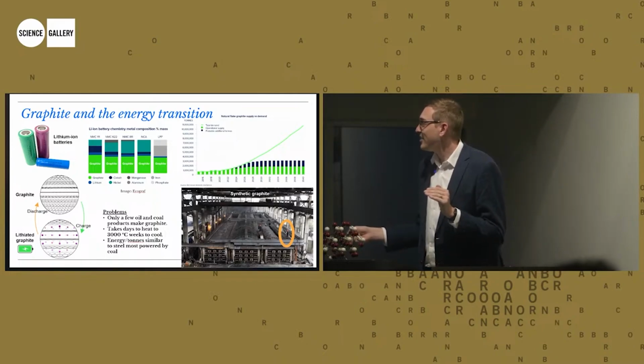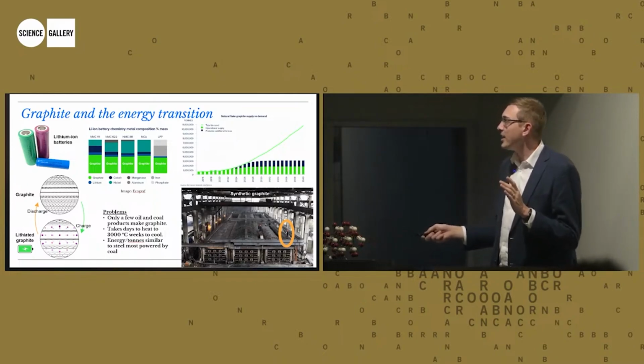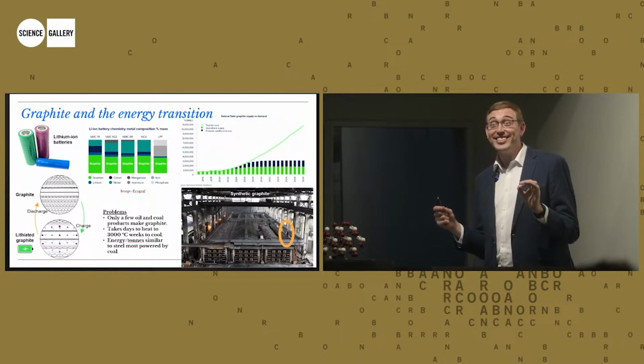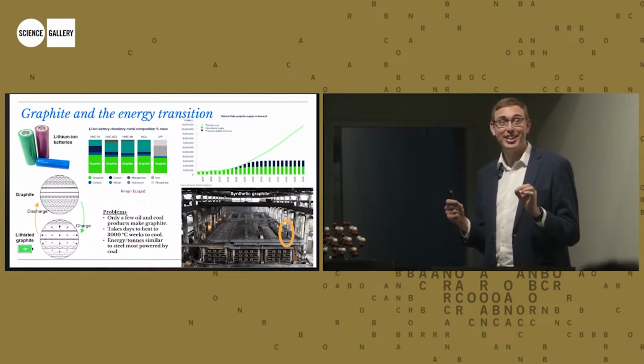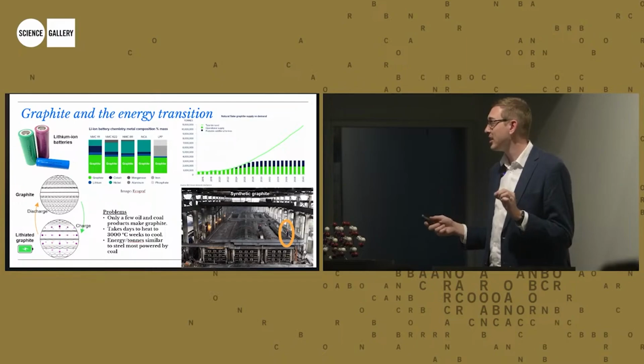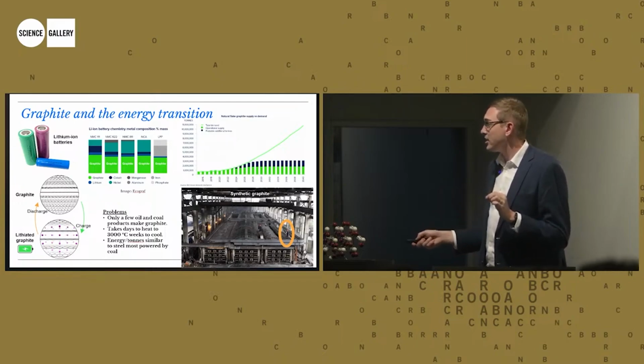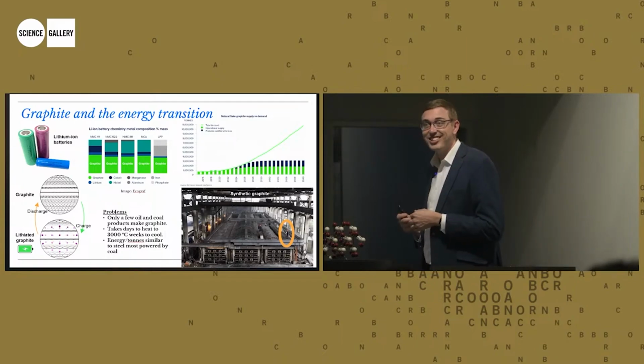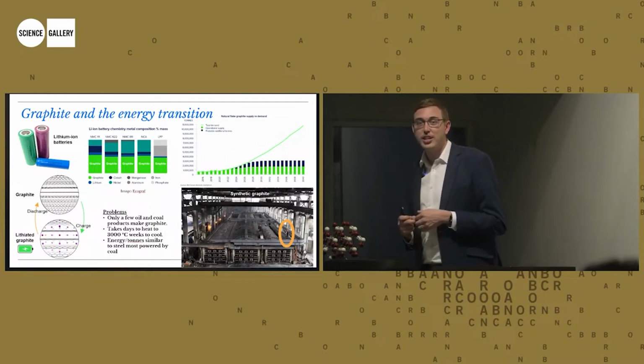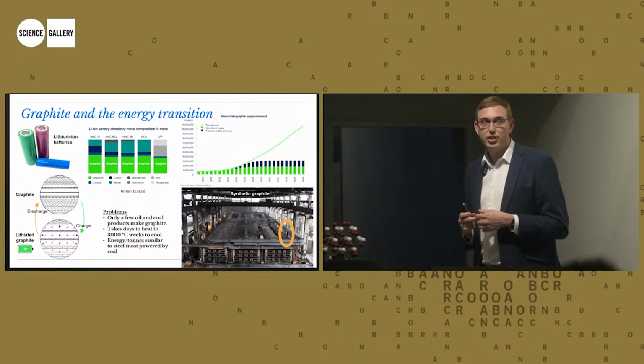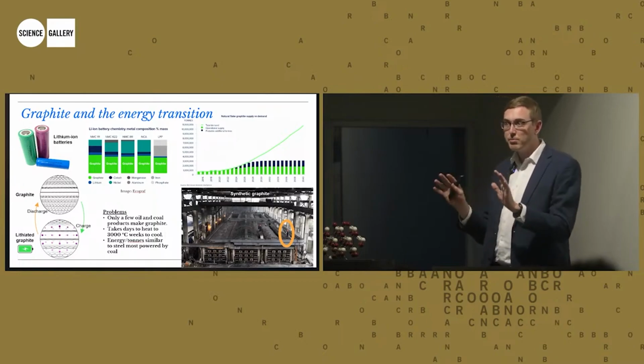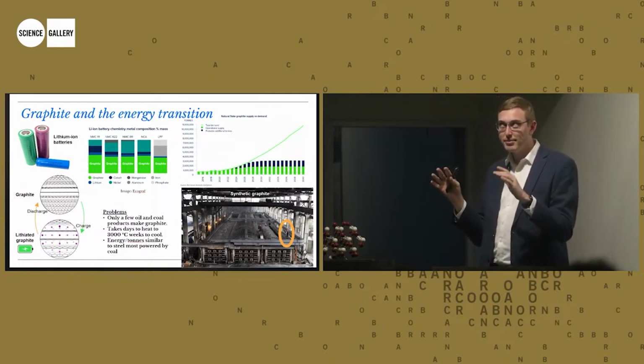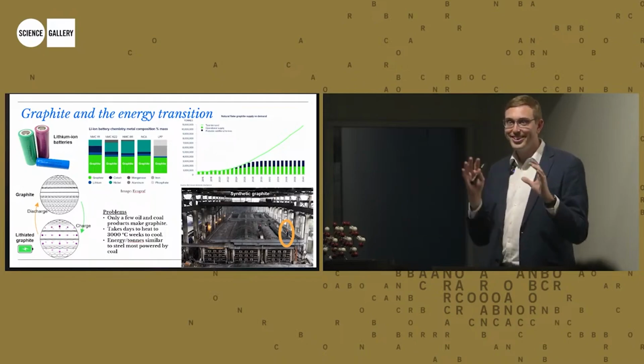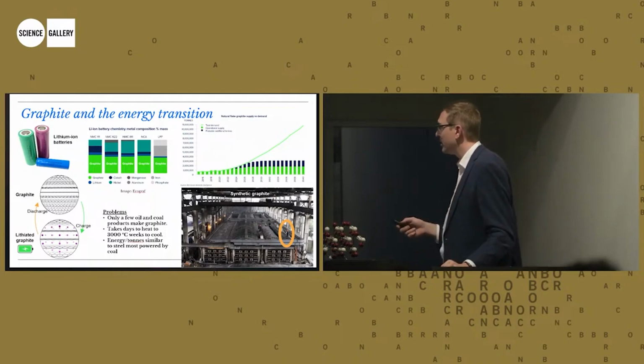It takes days, or at least a day, to heat up to 3,000 degrees. Okay, that's the temperature required to make graphite. Very, very hot. And the amount of energy it takes per ton is actually similar to steel. And most of graphite production is from coal. So you can see how this is a problem. But remember, it's still about 50% better than if we were to just burn it. So the electric vehicle is still better, but couldn't we make it even better is the goal.